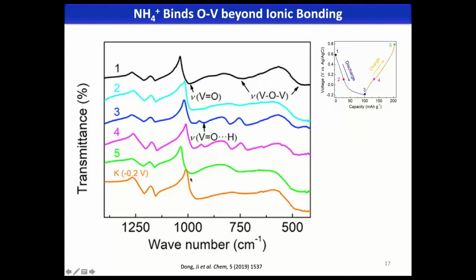And now, if you look at potassium, you have some red shift. That's it, just red shift, okay? And from that peak to this point. And now, if you look at ammonium, for 0.3, that is at the end of the discharge, the deepest SOC, the state of charge, you see this peak is split. That is split. It means actually the reaction or the interaction is not homogeneous, it's heterogeneous, right?